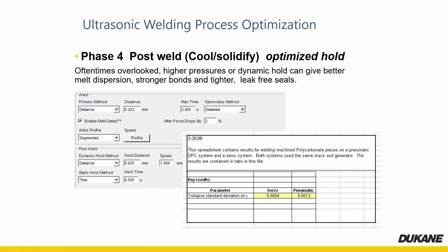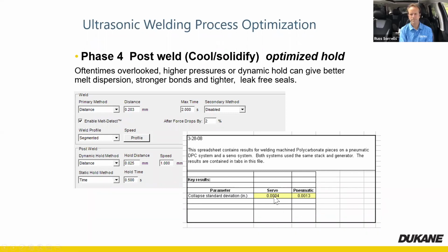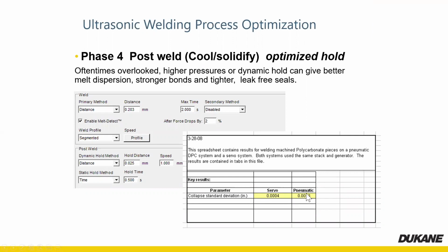We've done a bunch of studies on this as well, and what we found is that by doing this, we eliminate all of the stresses that you typically see created by this dynamic hold. All the stresses are eliminated from the plastic, where you just melted and reformed this material. Otherwise you are squeezing it and then breaking those bonds that you just created. By not collapsing any further, we don't add that stress into the joint, and it ends up being a much stronger joint in the long run. This is the other thing that's really important: the standard deviation of the weld distance. We can hold much tighter, much more consistent overall heights on these parts because we don't have anything dynamic. We are stopping when we need to stop. We are moving when we need to move, and we're adjusting that velocity when we need to adjust it.